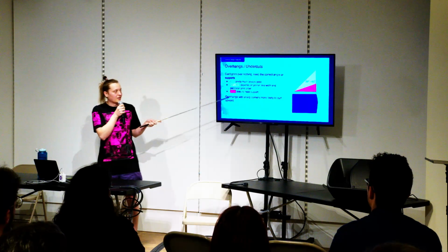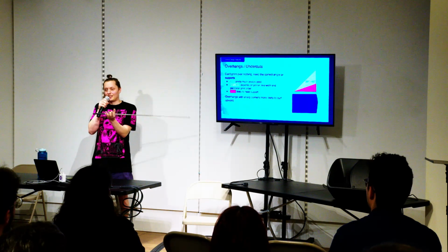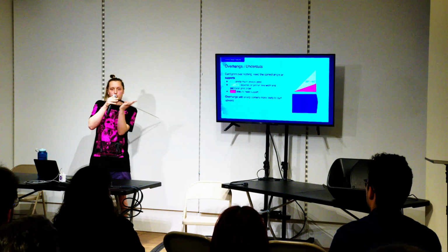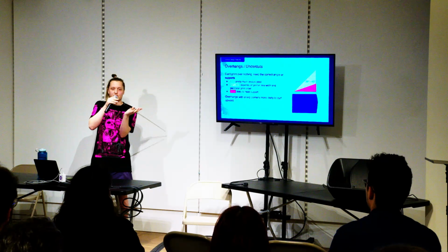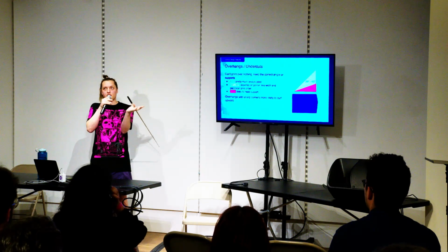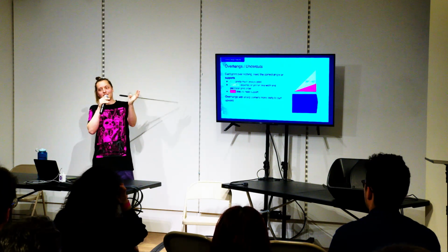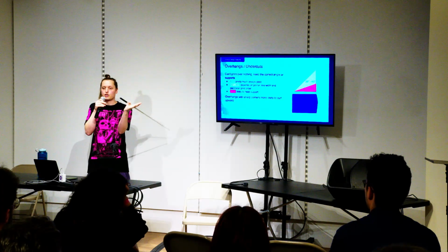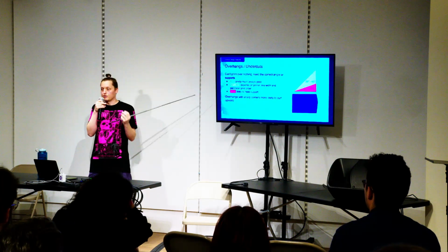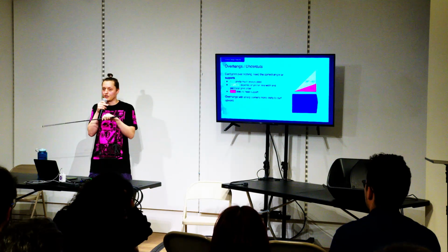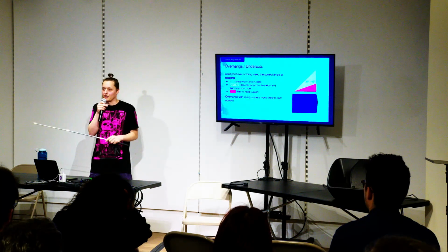Yes, and then overhangs with sharp corners. As there's less supporting the piece as it's trying to print, the plastic kind of tries to stick to the print head as it moves, and so those really sharp corners can lift up and usually cause print failures, as the tool head will then collide with that later and knock your print off the build plate.